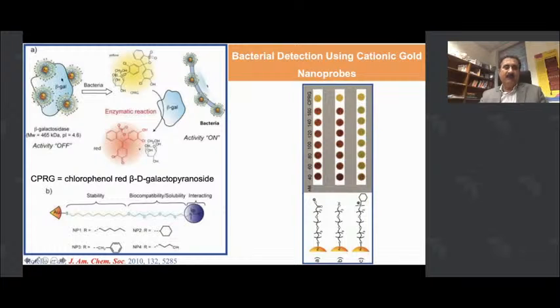So in this case, for example, you see this beta-gal protein, which is a large protein. When it is coated on these cationic gold nanoparticles, it loses its biological activity and is unable to convert this yellow substrate into red product. But in the presence of bacteria whose surface is negatively charged, these nanoparticles preferably go to the bacteria surface, and this beta-gal protein is released that can then convert this yellow substrate into red product. So in this way, you can develop a colorimetric method based on this protein and cationic gold nanoparticles to detect bacteria in drinking water. But note that both these proteins and gold particles are expensive.